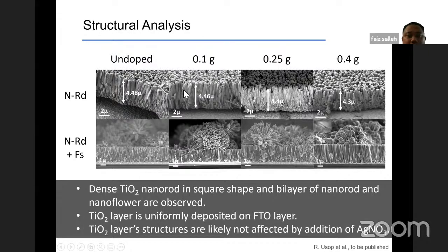This one is for the undoped. This second row is for 0.1 gram. This is for 0.25, and this is for 0.4 gram. So if we see here, we can observe the fabricated film still consists of the dense TiO2 nanorod in square shape and the bilayer of nanorod and nanoflower. So you can see the nanorod single layer, and also the bilayer consisting of nanorod and nanoflower. We also can observe that when we dope, the TiO2 is still uniformly deposited on the FTO layer. And then we also can observe that this TiO2 layer structure, either single layer or bilayer, is likely not affected by the addition of the AgNO3 doping, even up to 0.4 gram.